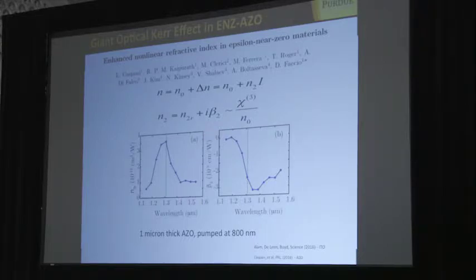And the good thing about this is that independently, two groups working with entirely different materials, Bob Boyd's group did ITO and we did AZO, using very different techniques. They used Z-scan, we used the pump-probe technique. We both obtained a really dramatic change in nonlinear response at the ENZ point.